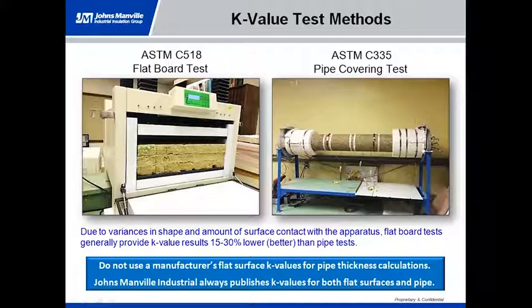Again, we're doing the same thing. We have a hot heat source, which is the pipe, and then of course the cold side is the temperature of the room, which in most cases is somewhere between 70 and 80 degrees. Now the difference is, if I want to get it tested at mean temperature with C518, I only need a 100 or 200 degree temperature difference. So if I'm testing to a 700 degree mean temperature, I might have a hot plate of 800 degrees and a cold plate of 600 degrees.